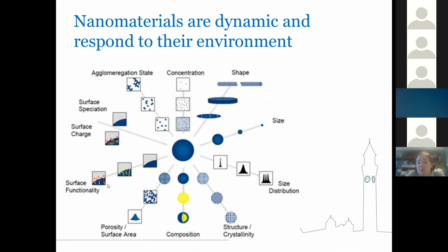So if it binds to proteins or other biomolecules present, that gives it a new identity that changes it from the synthetic identity to a biological identity. We can also have changes due to other processes, so physical processes like dissolution. That can lead to changes in the composition. For example, if some part of it dissolves faster than another, it can lead to changes in porosity or the size of pores or the surface area, but also changes in size due to dissolution, or even changes in shape. So we'll often have processes where the particle will start to dissolve, for example, and then potentially reprecipitate as something different.